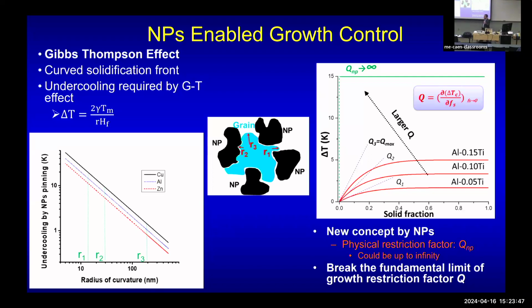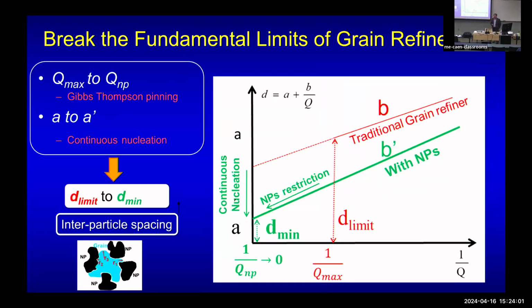Unlike the traditional free growth theory, which relies on chemical methods for restriction, we have physical nanoparticles to restrict growth, and they're very effective. By this way, we can break the fundamental limit of grain refinement in traditional casting. Traditionally, the reason we couldn't get small grain is that growth stops here, the Q is small, and your grain size is dictated by this process. You couldn't realize your full potential.